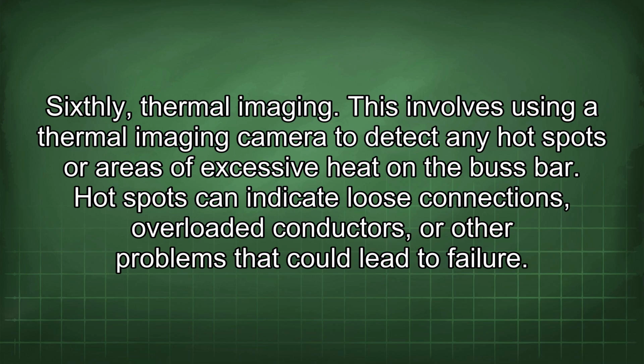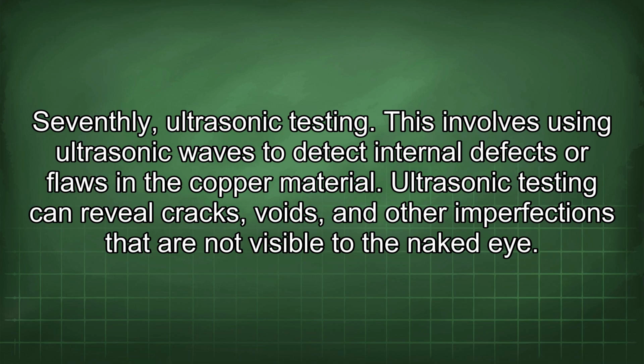Sixthly, thermal imaging. This involves using a thermal imaging camera to detect any hot spots or areas of excessive heat on the bus bar. Hotspots can indicate loose connections, overloaded conductors, or other problems that could lead to failure. Seventhly, ultrasonic testing. This involves using ultrasonic waves to detect internal defects or flaws in the copper material. Ultrasonic testing can reveal cracks, voids, and other imperfections that are not visible to the naked eye.